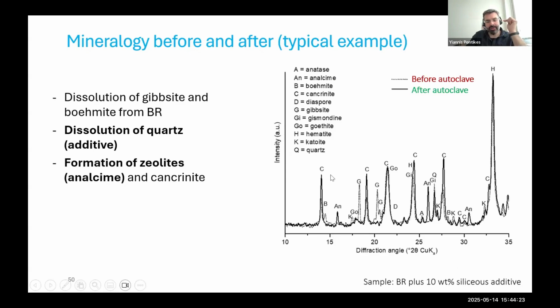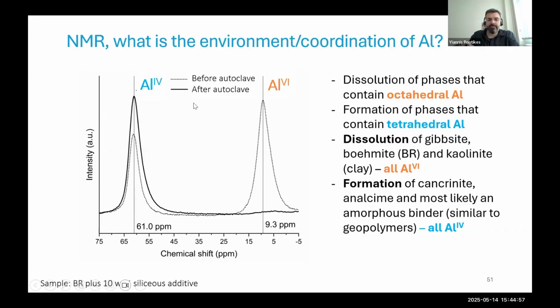But first, let's understand what is reacting. So again, inspiration was the Bayer process. In the Bayer process, when you do autoclaves, and they're different because then it's a liquid, you dissolve the alumina phases, gibbsite, boehmite, diaspore. Same thing here. You will dissolve also silica, like quartz, same thing here. And you see with the lines before and after autoclave. And depending on the conditions, you will form different things, sodalites or zeolites, as we have seen also in our process. Now, from an NMR perspective, you also see clearly that alumina is dissolving and new alumina is forming.